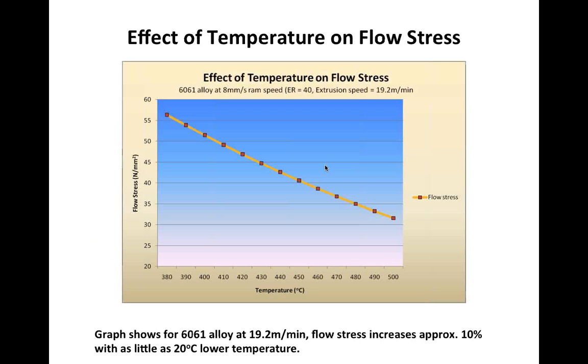So we just reviewed that the temperature in extrusion is always changing, and what the temperature will do to your flow stress. You can see from this graph that when the temperature is colder, for the same alloy that you're extruding, the flow stress is going to increase. And you can see on the scale that every 20 degrees Celsius, or 40 degrees Fahrenheit, drop in temperature is about a 10% flow stress increase.